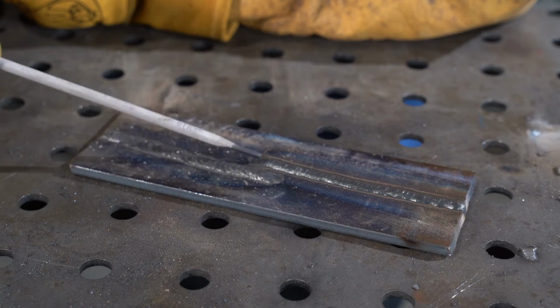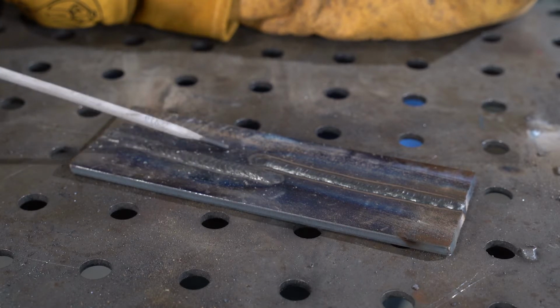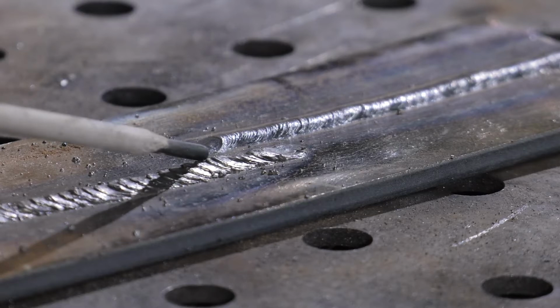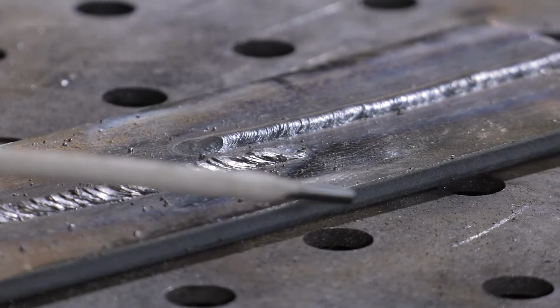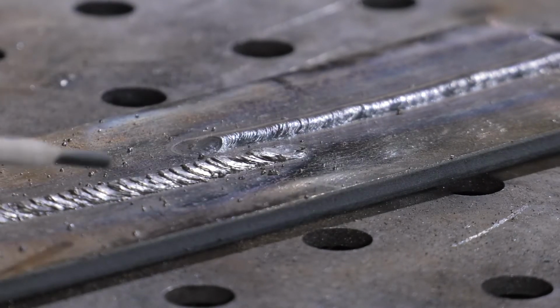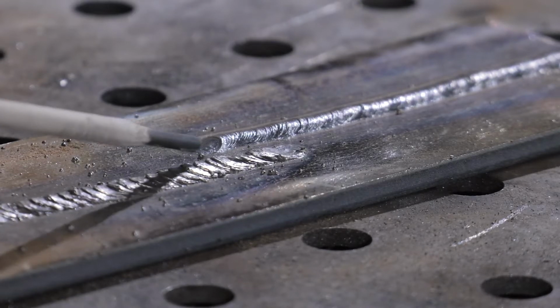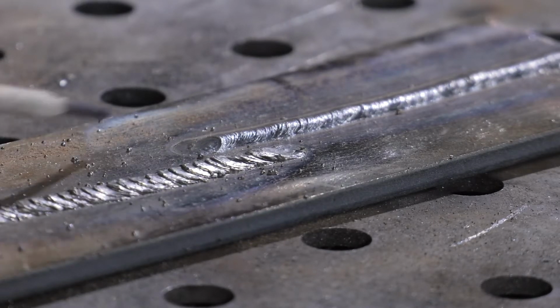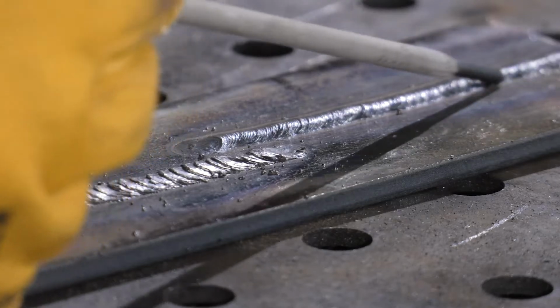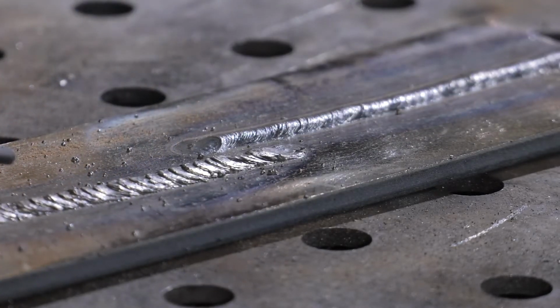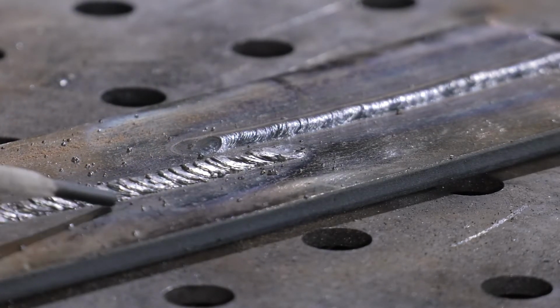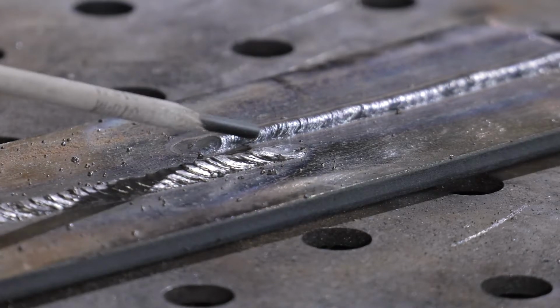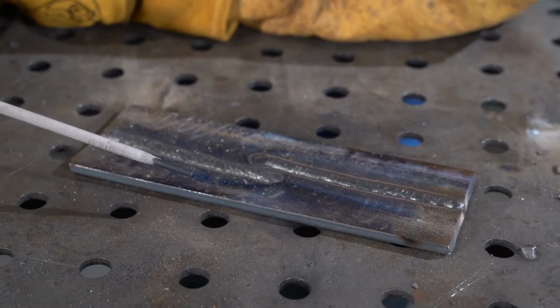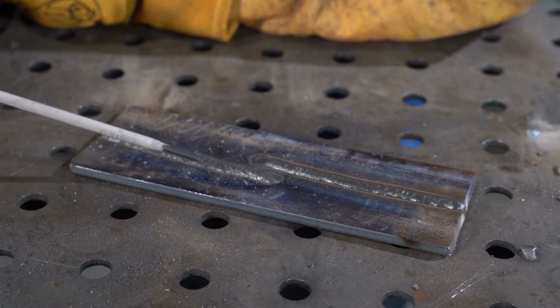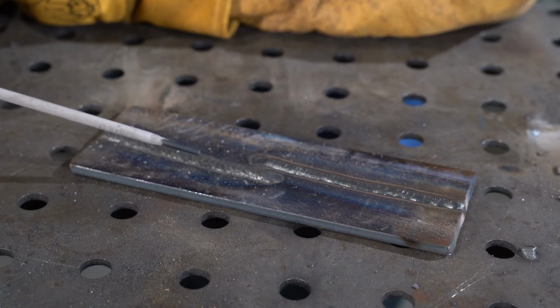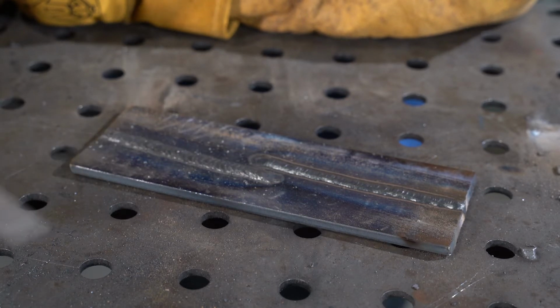These are both stringer beads here, and basically the stringer bead is a narrower weld, not going much wider than the diameter of the electrode. And these are the profiles we're after. Convex profile with uniform toes of the weld here. And what we're looking to see is there's no gouging or undercutting along each edge, and none is present. So these are acceptable welds and something we'd like to see and produce over and over again.